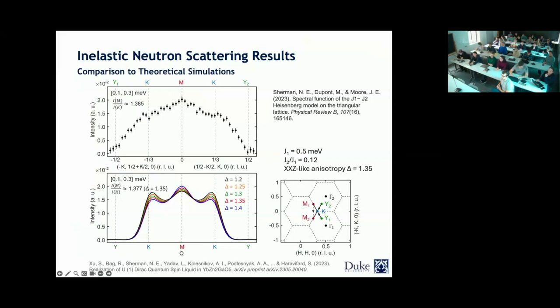By doing this, if you have an isotropic system, basically you would have all of these peaks at the same intensity. However, when you start to have anisotropy, we thought that this effect is coming due to the anisotropy. We looked at the intensity at the M point and the K point, and we got that the ratio is about 1.38. So they also ran the model based on different delta values, and they figured out that a delta value of 1.35 is going to give us the same intensity ratio between the M point and the K point, and then started to implement this delta value into their model for the J1, J2 model, okay?